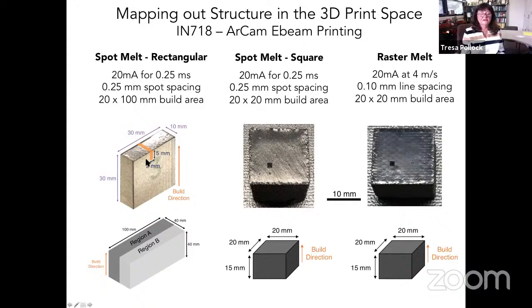And so what we have here is a spot melting strategy. And here are the details of the build area. And what we're trying to do here is more or less hold the beam printing conditions constant, but vary something else about the build. And one might assume, and people often do assume, that since you're operating at basically constant conditions, that you should develop the same structure. And instead, what you'll see is that all of these details matter a great deal with regard to structure development. And so in this particular case, you're going to see a data set where we've sectioned a piece from the very last part of the build where we've made a spot melt in this region.